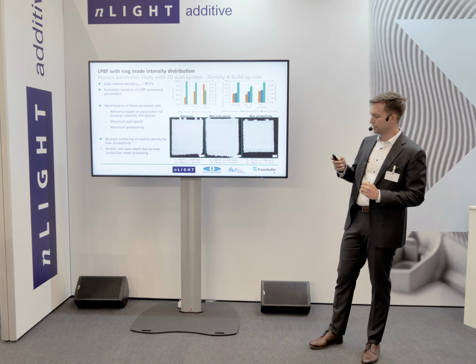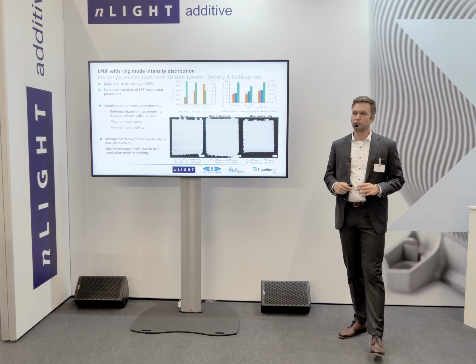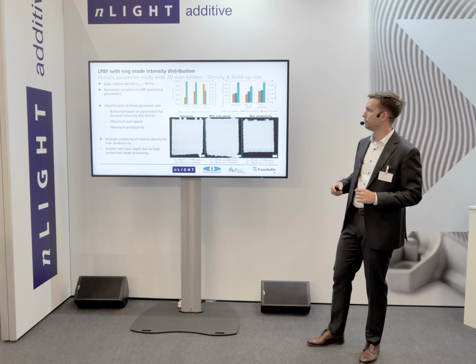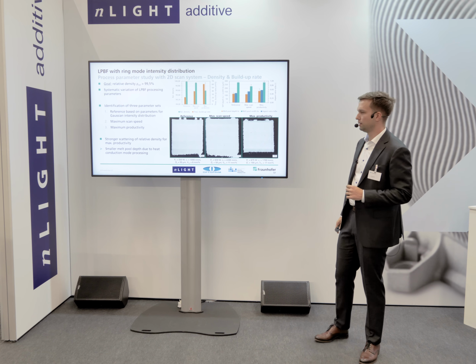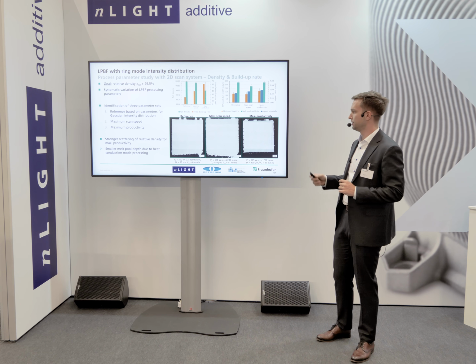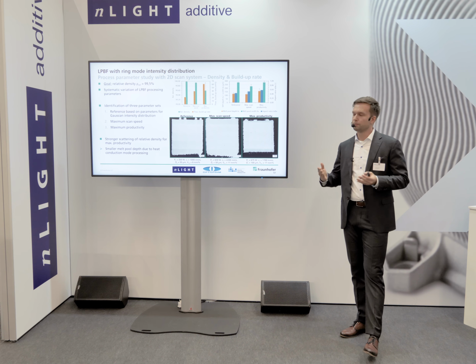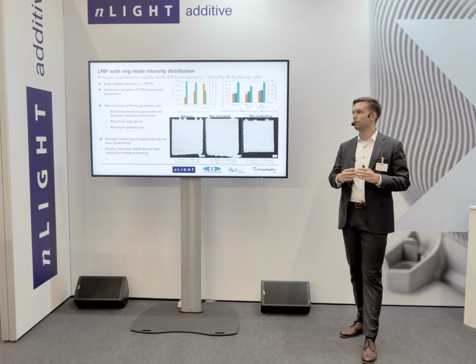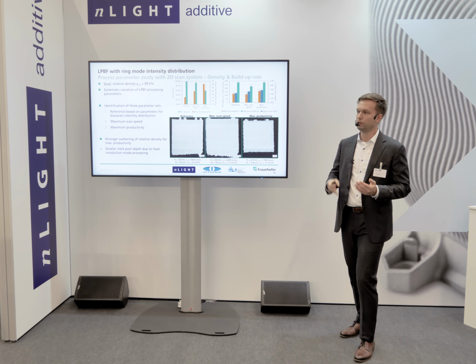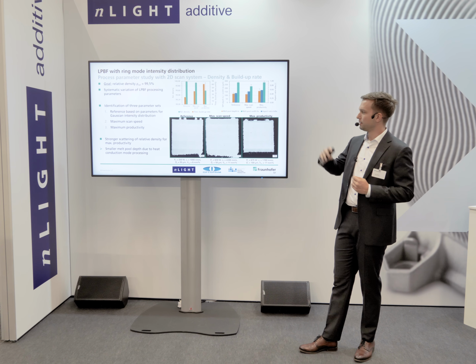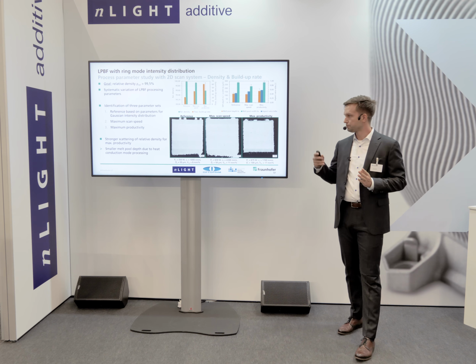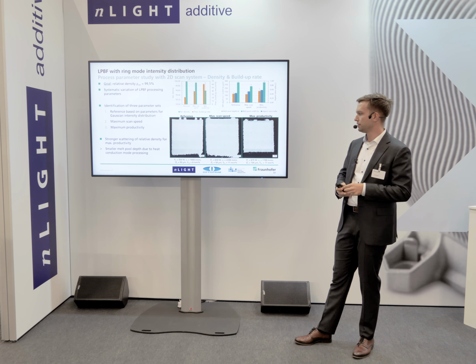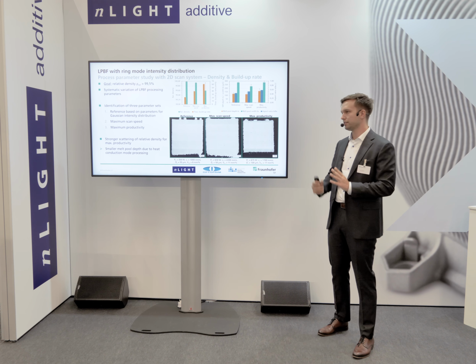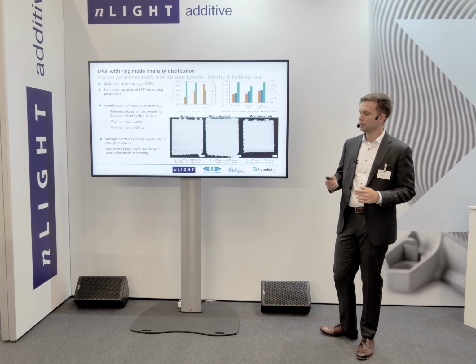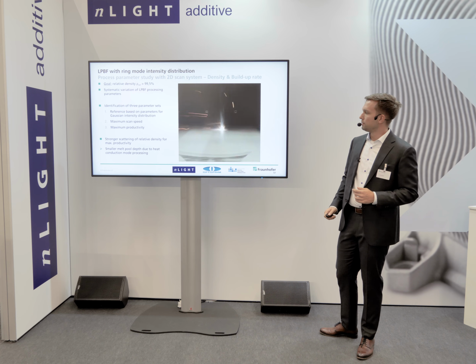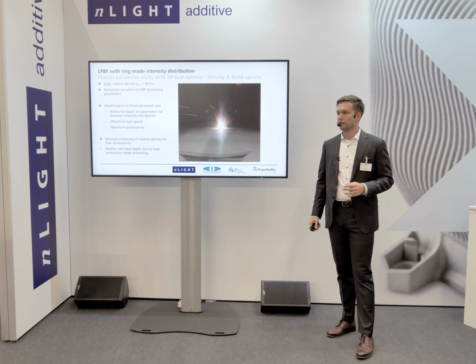And when you then analyze the results, you see density works for all of them, so 99.5% is not a problem. You see some stronger scattering with regard to the relative density when you look at the max productivity, because, of course, it makes sense that when the melt pool is more shallow and wide, it is more difficult to really melt high layer thicknesses, but the max scan speed works really well. So compared to standard processing parameters, we have a scaling of approximately factor of 2 just via the scan speed compared to our reference. And that was our starting point to then look into the final product itself.